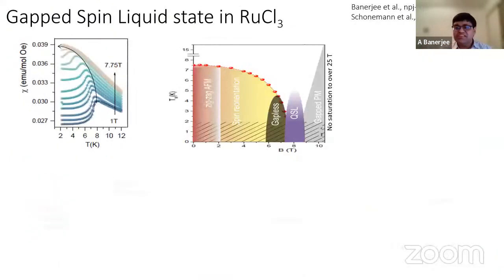But how to nudge this material into a pure Kitaev state? What you can do is apply a magnetic field. So let's look at the field-dependent phase diagram. So this is temperature and this is field. This is the field and temperature-dependent phase diagram that we measured. At low fields you have this zigzag antiferromagnetic state, which goes into a gapless state, to a quantum spin liquid state, is what we figured out.